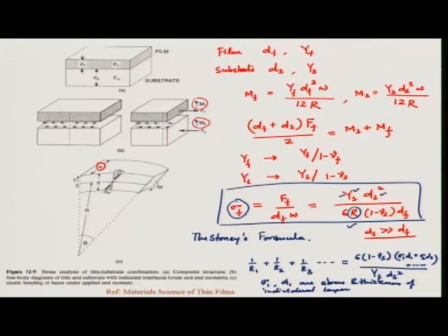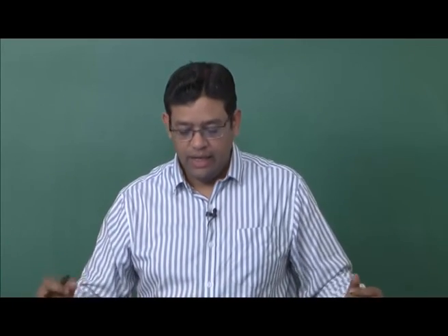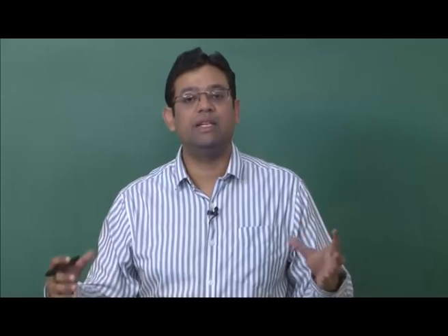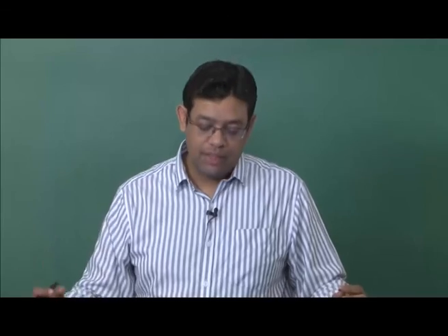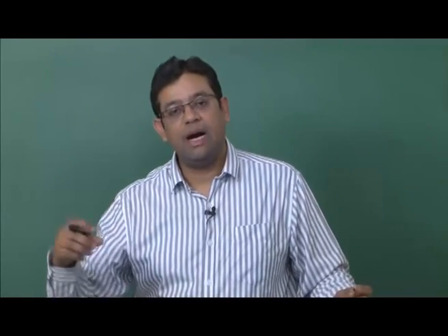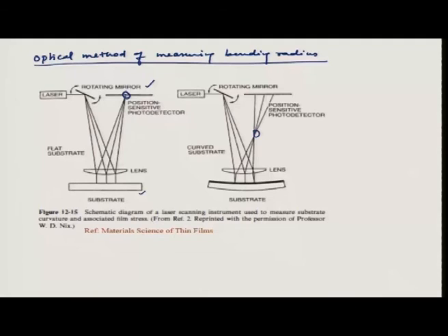This is particularly important because sometimes once you deposit the film and it has a high amount of stress, over time it will start to peel off. It will crack if the film is under too much stress. As we have seen for epitaxial films, these stresses or strain in the film are relaxed by formation of islands, which, if we want to avoid, we need to minimize the thin film stresses as well. So, this is a method of measuring thin film stress.